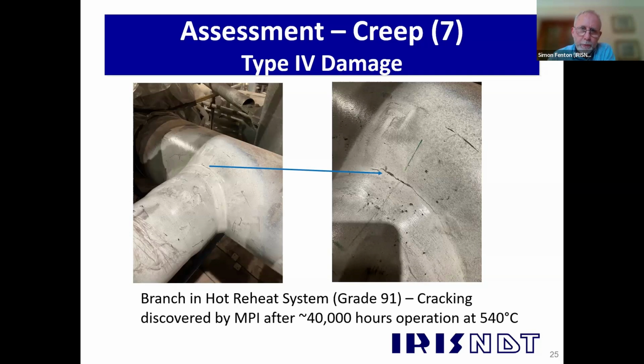And it was a creep crack. But we only found the creep damage at that one position on the flank, a so-called flank position of the branch. At the crotch positions at 90 degrees from that crack, going either way, and the other flank position underneath, there was no creep damage at all. So no cracks and no creep damage detected by replicas. So that tells me there's a large system load acting on that, as well as being a shortfall in the design and the fact they've used grade 91.